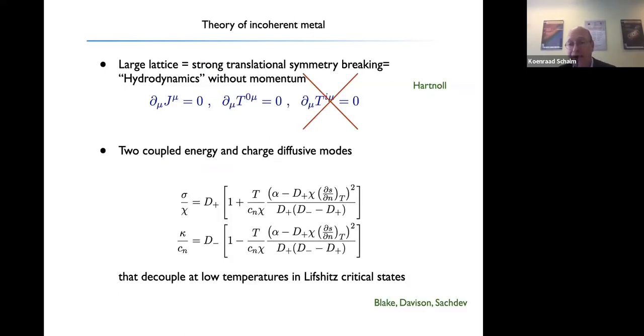The more appropriate way to analyze it was emphasized in particular by Hartnoll, who wrote a beautiful theory of incoherent metals. If you have this very strong translational symmetry breaking, which you have in the presence of a large lattice, you can still do a hydrodynamic analysis, but it's hydrodynamics without a momentum current. You still have a conserved charge, and you still have a conserved energy current, but there's no longer a conserved momentum current in the system. And that means that the analysis becomes a little bit different.